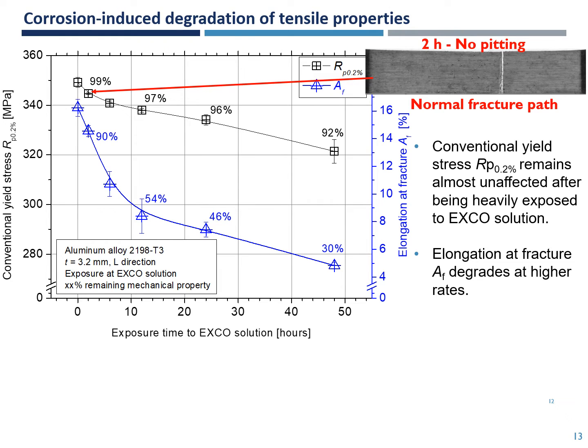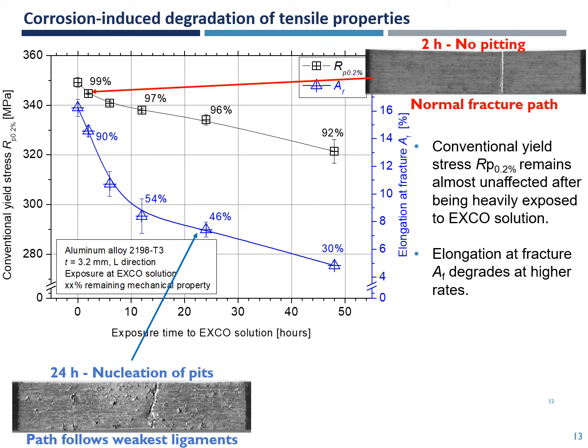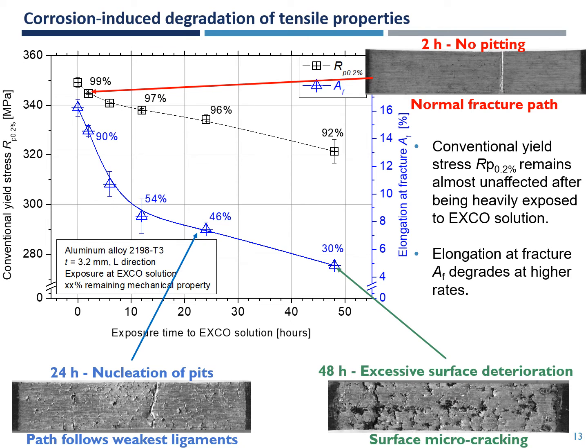Regarding the surface morphology of the corroded specimens, it was found that after only 2 hours of corrosion exposure, no surface pitting is evident. However, after 24 hours, the nucleation of pits is evident on the corroded surfaces, and after 48 hours, an excessive surface deterioration with the formation of surface microcracking is evident.